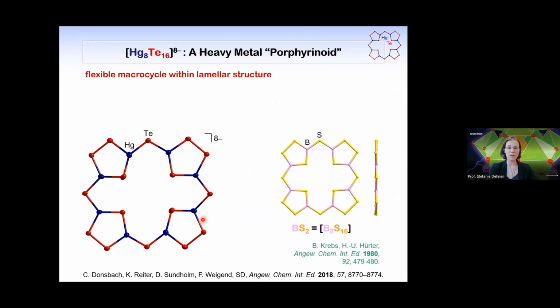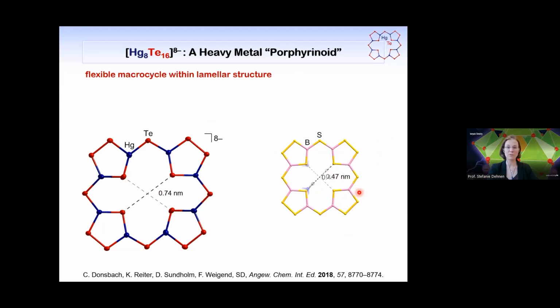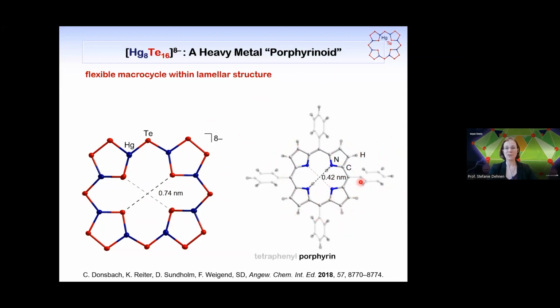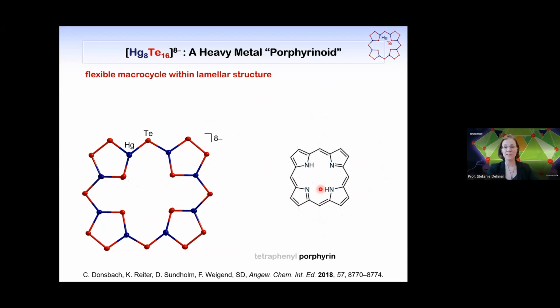It is the second known, I call it a porphyrinoid inorganic cluster molecule, beside the simple structure of boron disulfide, as we found out, but this is a neutral compound, so you find a flat molecule in this kind of compound. And of course, the dimensions are much larger with mercury and tellurium, so if you compare, it's nearly double the size, and this is a scaled representation of the atoms as well. And of course, we find the structural relationship with porphyrin itself. So here you have the structure of tetraphenylporphyrin, and you see again that the dimensions are very different, but the overall topology is exactly the same.